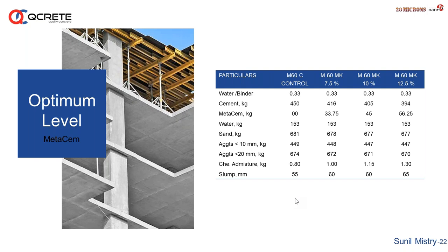And cement we kept 450 in a control concrete, whereas we replaced cement by 7.5%. The next design mix we kept the cement reduction ratio of 10 and then 12.5. You can see here the control mix has 450 kg cement, whereas replacement of cement by 7.5%, that is 33.75 kg, we added Metakaolin and reduced cement to 416. Then the next is 405 with 45 kg, and the last one is 394 with 56 kg of Metakaolin. The idea behind this is to optimize the dose actually.